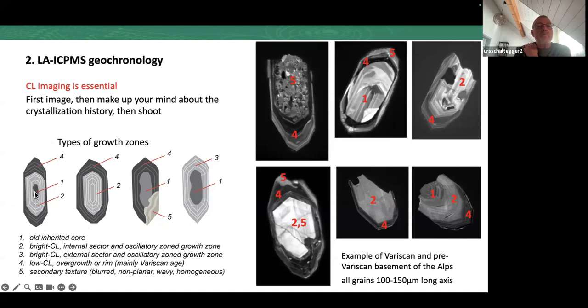Then shoot into zone 1, zone 4, zone 5, after you have defined these growth zones. So 1 would be an old core, is present here, is present here. 2 would be a growth zone, sector and oscillatory zone. Sometimes there's no old core, and sometimes this zone is also outside at the outermost rim. So later on, I realized that actually 3 and 2 is the same. And then the whole thing is overgrown by a zone 4, which has a low luminescence, so high uranium. Sometimes 2 and 3 are lacking. So this is directly overgrowing 1.